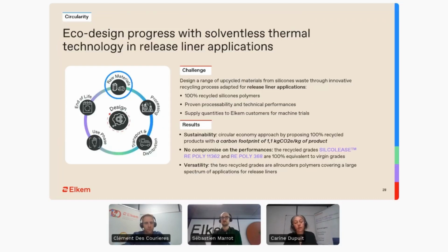So to conclude, Elkem successfully tackled the challenge of designing upcycled materials from silicone waste through an innovative recycling process tailored for self-adhesive and release liner applications. These initiatives led to the creation of 100% recycled silicone polymers, which demonstrate proven processability and technical performance. The recycled grades SILCOLEASE Re-Poly 11362 and Re-Poly 368 are equivalent to the virgin counterparts, ensuring no compromise on performance.